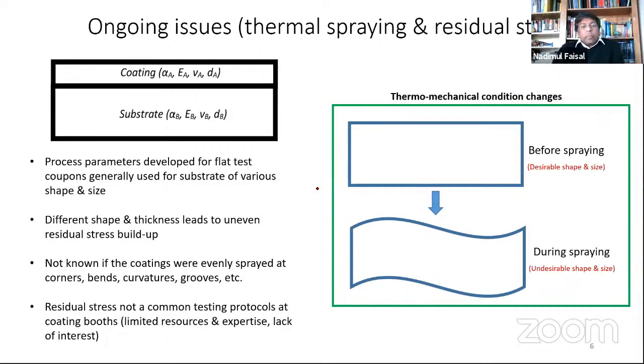So most of the research and development work done is on flat test coupons. However, when you deploy in real life, they are not on flat substrates. They would have different geometry, shape, and size. And because of that, that leads to uneven residual stress buildup. A lot of things are not known if you're spraying on corners, bends, curvatures, or grooves. And from my experience, I know that residual stress is not a common testing protocol in industry, either because of lack of resources or expertise, or maybe lack of interest.